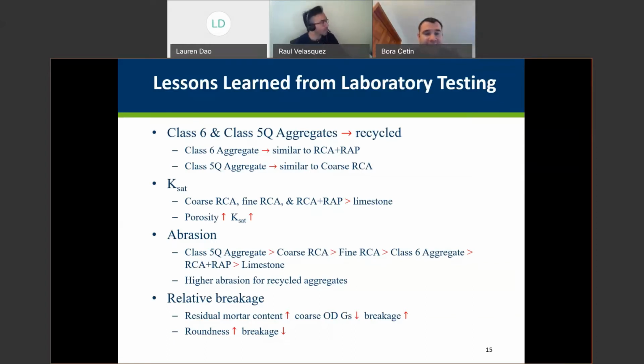One thing that we may say with the abrasion values, RCA seems to have higher abrasion, and the limestone has better abrasion resistance, which is expected because, as we will get to, some of the mortar materials look like aggregate-size shaped materials, but they are not actually aggregates. They are just clumps of cement particles combined with finer aggregates and finer sand materials that turn into coarse gravel-size aggregates. And when you apply the abrasion, either through gyratory compaction or through the LA abrasion, those mortars are broken. That's why this study found that aggregates with recycled concrete have a little bit higher abrasion compared to limestone.